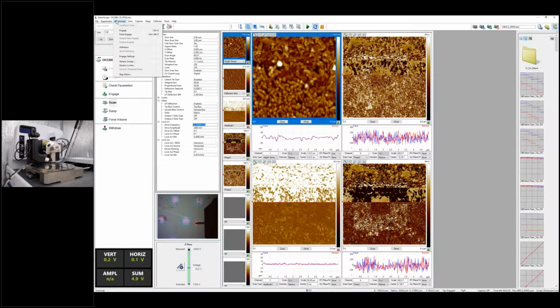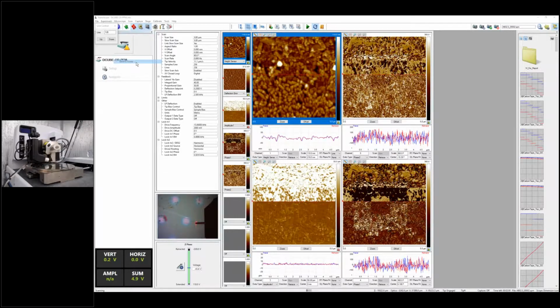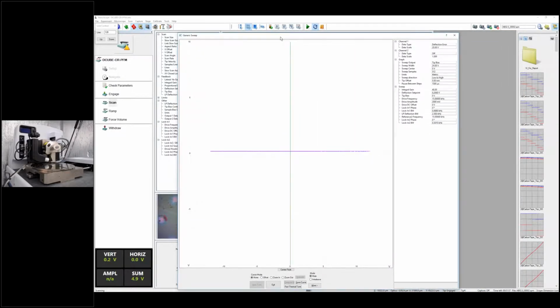So we can just do a quick sweep on top of the sample. For this material, basically we have piezo response almost everywhere. So no matter where you do the sweep, it's okay. So what we're interested in is the amplitude, because we're trying to find out the contact resonance frequency. And what we're trying to sweep in the X direction, of course, quite obviously, is frequency.